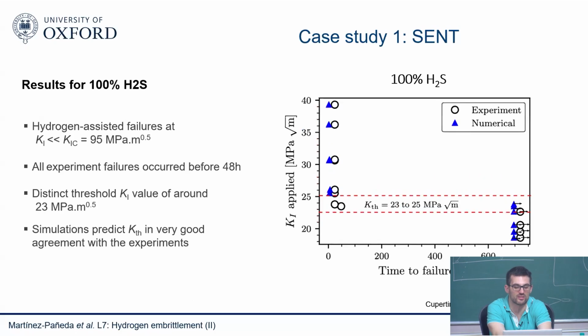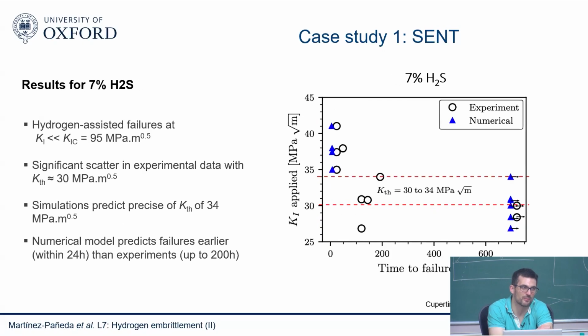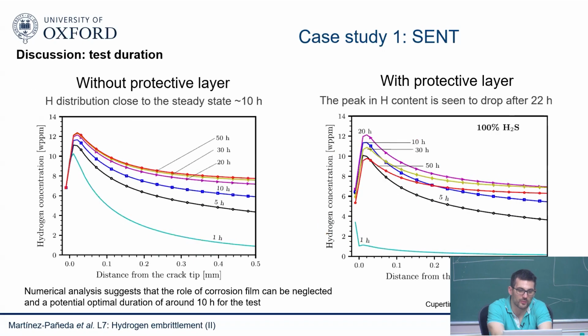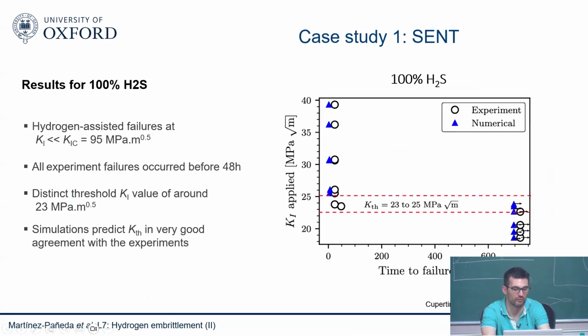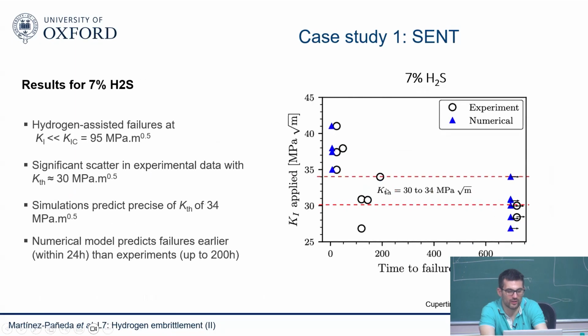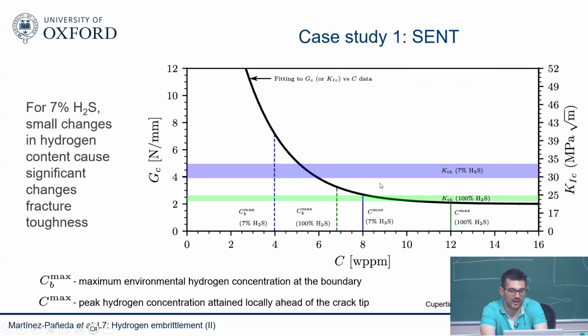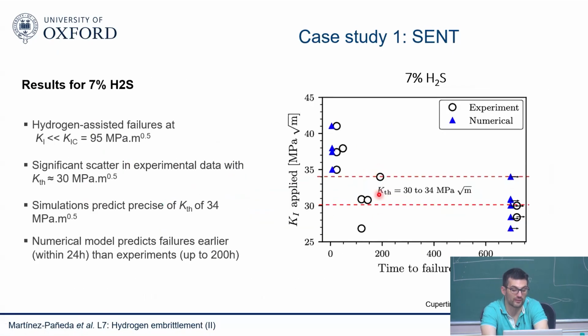I guess we saw that the model seems to agree with experiments, particularly for the 100% H2S. For the 7% H2S, there's a bit of scatter with experiments, so it's a bit more difficult. So what we did is we interrogated the model. First we said, okay, forget about the fracture. Let's look, first of all, at the hydrogen distribution ahead of the crack, because one of the key questions is, how long should the test last? Should the test last 700 hours? Because all the failures happen relatively early, for example, in this case, all in 48 hours, but they still do tests of 700 hours. But at the same time, they can see that some of them fail after 200 hours, and some of them that are supposed to fail didn't fail, so they're a bit concerned about how long they should wait. So this 700 hours comes a bit out of the blue.